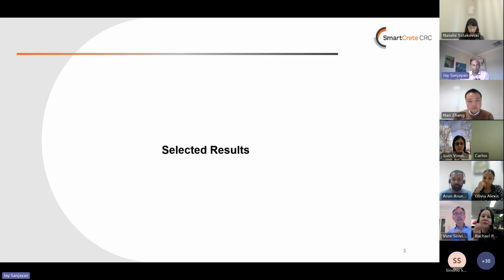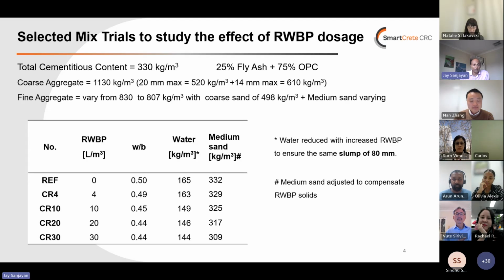Because of the time limitation, I'm just going to show some selected results of the research that we have been doing now for more than a year. So this particular slide shows 5 different concrete mix designs. If you look at the first column, that's where the reclaimed paint, we added 0, that's the reference, and then 4 liters, 10 liters per cubic meter of concrete, 20 liters per cubic meter, 30 liters. So those are the 4 levels of reclaimed water-based paint dosage.